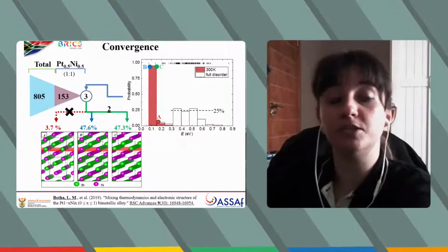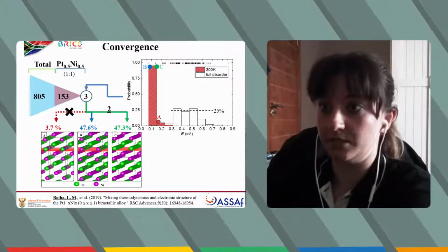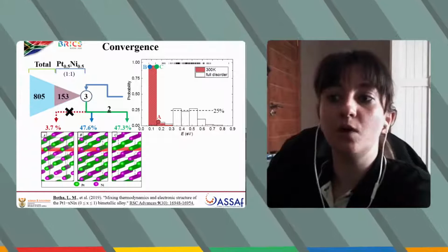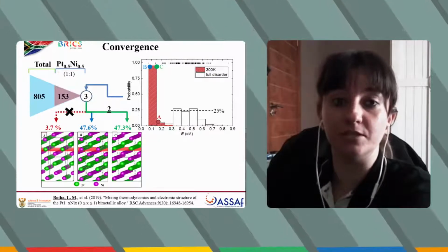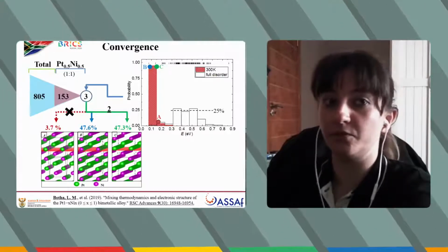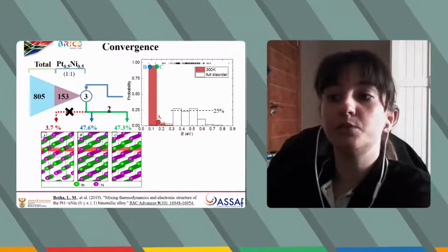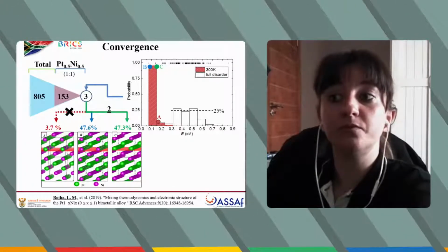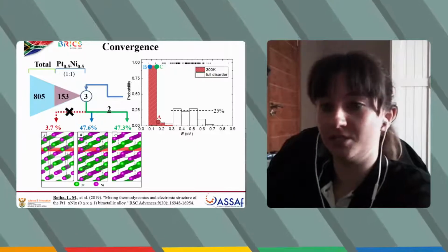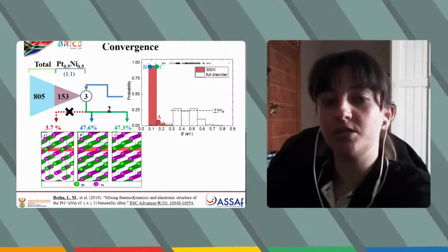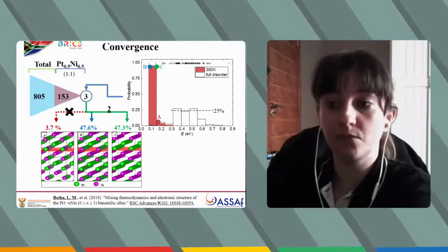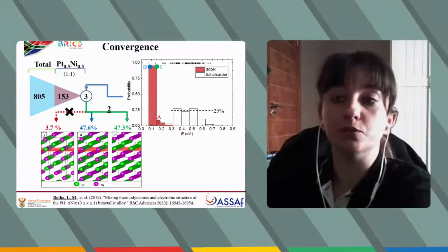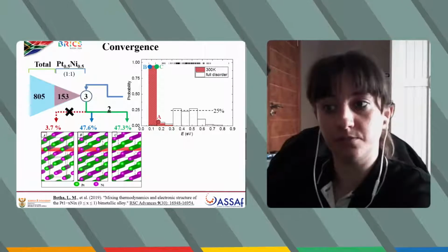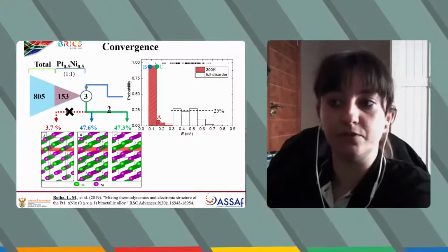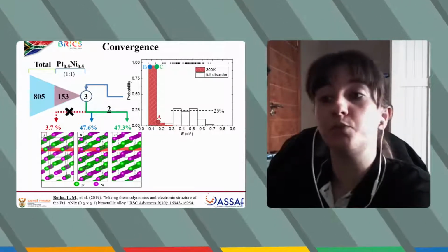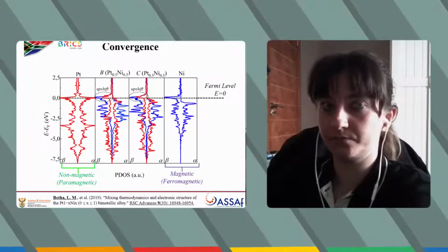805 unique configurations were identified with SOD. This was narrowed to 153 configurations using mixing thermodynamics for the 50%. Using probability distribution, this number was further narrowed down to 3 configurations, A, B, and C, which occur at 300 Kelvin. Higher temperatures were not used due to low probability of occurrences. Therefore, the B and C configurations will be used to study electronic properties in terms of the D band.